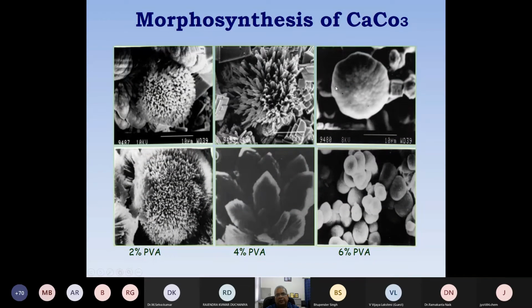The row on the top is showing the three morphologies of calcium carbonate that we could develop in 2%, 4%, and 6% PVA. And when we carried out X-ray diffraction, we found that under 2% we got the calcite phase, in 4% we got the aragonite phase, and under 6% we got the vaterite phase. So three phases.